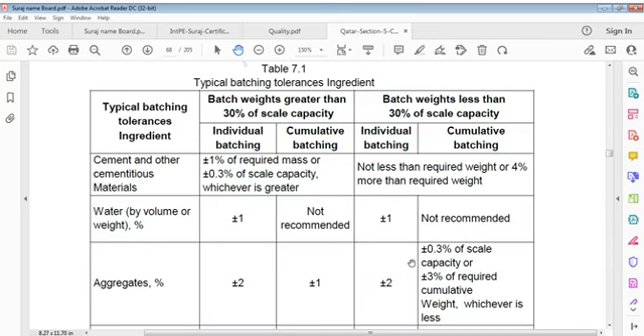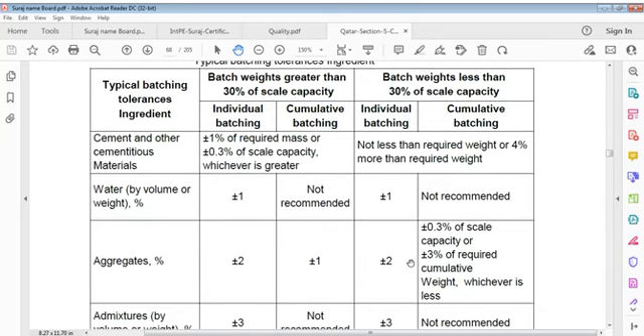These are the only items. In this case, cement and other cementitious materials are plus or minus 1% of required mass or plus or minus 0.3% of scale capacity, whichever is greater. This is when the batch weighs greater than 30% of scale capacity. Individual batch and cumulative batch, also for weight batch less than 30% of scale capacity, it is not less than required weight and not more than 4% more than required weight.